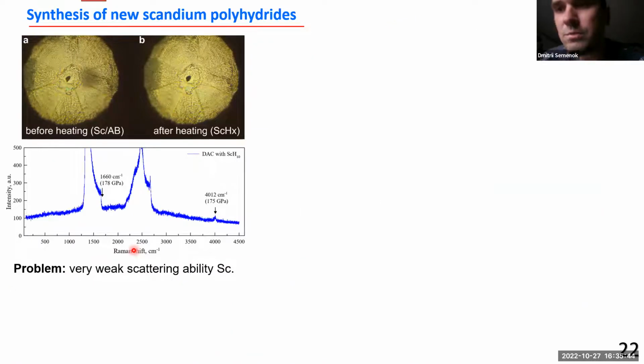And we decided to check these theoretical predictions and placed a very small particle of scandium, this black spot, on the diamond anvil, and compressed it to about 180 GPa. You can see the Raman signal completely clear. We can see only hydrogen after laser heating. It's here and no other signals. So no signals from ammonia borane, no signals from decomposition products of ammonia borane, except the diamond and second order diamond. We cannot see anything else.